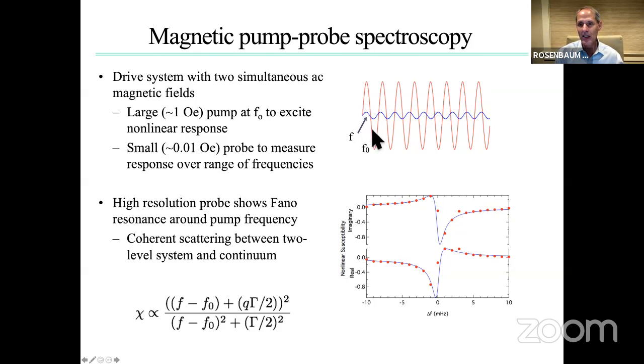We're going to burn holes in the spectrum by exciting these clusters, these 2-level systems, which are spin clusters effectively composed of a few hundred spins, from their ground state into their excited state. And how you do this is you use a small amplitude excitation to measure the equilibrium property, and then you fix a frequency at f0 and you excite the nonlinear response. To give you an idea of the kind of energies you're talking about, you're only talking about a Gauss or an Oersted excitation amplitude. So you're not talking about very much magnetic field, but it's enough to burn a hole. So this is about half a Gauss. You can see the nonlinear susceptibility.